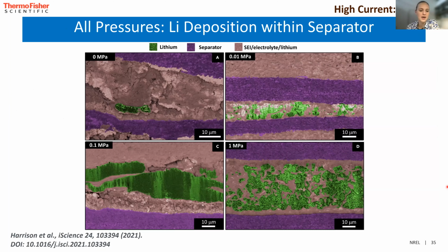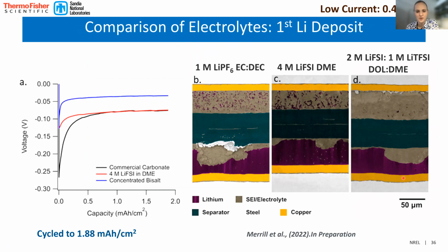This one is just showing the electrode deposition of lithium within the separator and how common that was, and how we usually actually saw a lot of interconnected networks of larger lithium grains within the separator. But it is a problem with this separator combination with that electrolyte. The other thing that we did was we looked at a variety of different electrolytes and tried to understand failure from this system level scale.